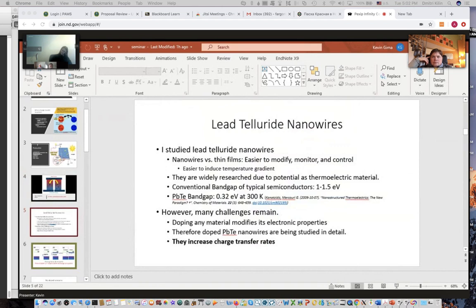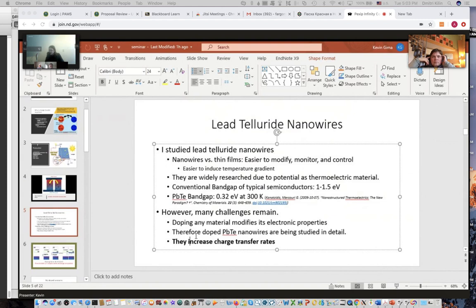So what scientists do is that they basically study doped lead telluride nanowires. They dope these nanowires, and doping is essentially introducing an impurity into a material. So they might replace some of the atoms with iodine and sodium, which is what I'm studying. Scientists and researchers have found that when you dope lead telluride nanowires, they increase the charge transfer rates. So one of the main goals of my project is to confirm that, to see if the doping process improves the charge transfer rates in my computational study.